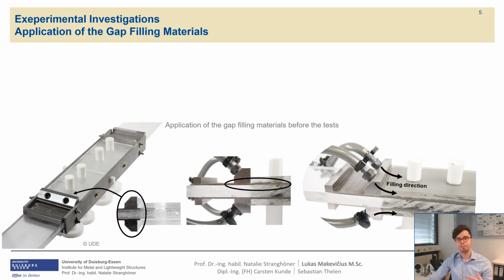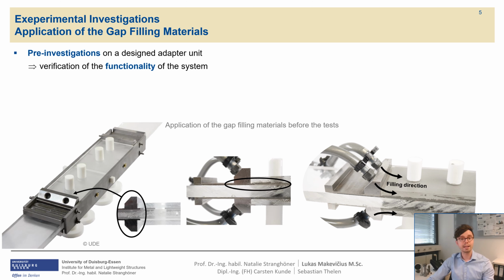One of the most important matters in the project was to guarantee the reproducibility of the application process and, of course, the adjustment of the desired thickness of the gap-filling material in the connection. For this reason, a special adapter unit has been designed and verified in the pre-investigations. As can be seen in the pictures below, it was decided to create special openings with threads and to inject both materials, the MM1018P, the pasty version, and MM1018FL, the liquid version, manually using cartridges and applicator guns.